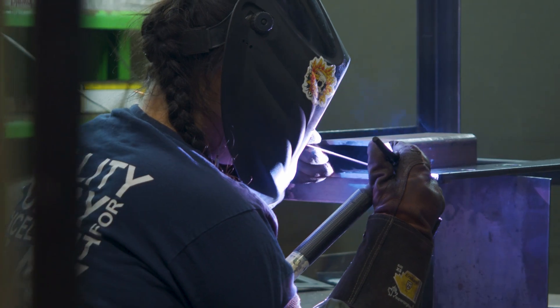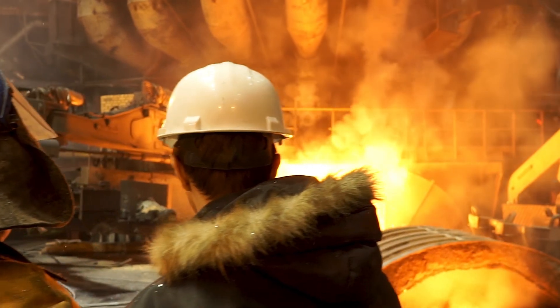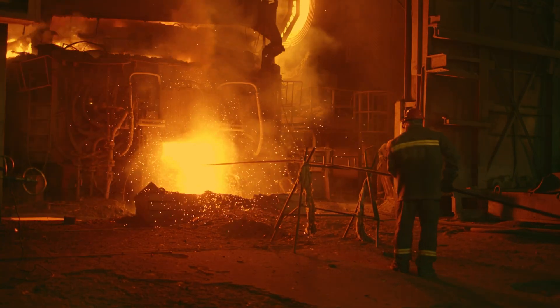The one disadvantage is that in an extremely abusive environment — for example, we literally drove over both a steel beam and a composite beam with a forklift — the steel beam certainly dealt with that better than the composite. In addition, there are heat restrictions. We could engineer a steel lifting solution to deal with thousands of degrees, whereas composite has a temperature limit of 150 degrees. Caldwell builds mill duty equipment for steel mills and hot situations — in those cases, I would not apply Duralight.